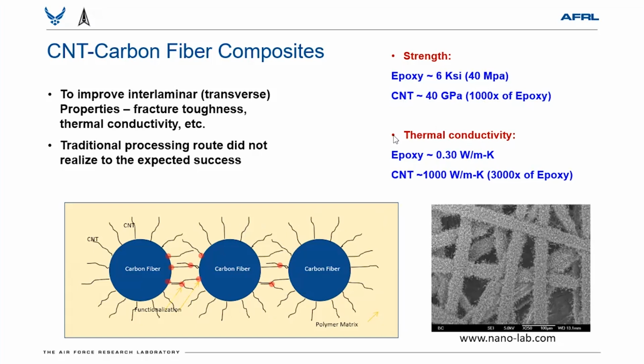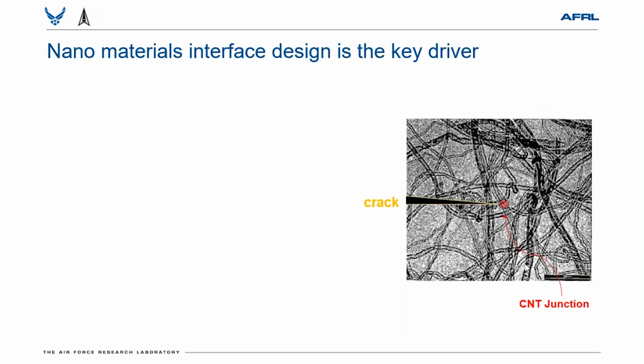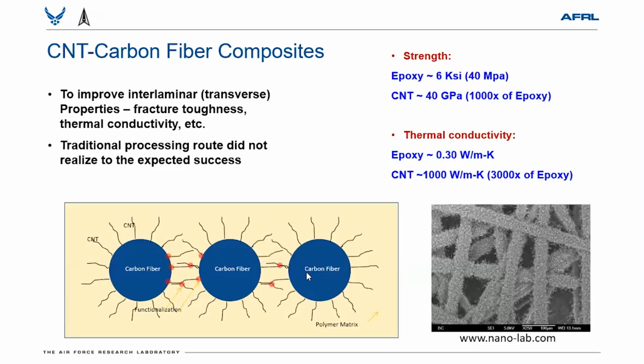Same is the story for thermal conductivity. Thermal conductivity for epoxy is 0.3 watts per meter Kelvin, whereas the CNT conservative estimate is 1,000 watts per meter Kelvin. So even when 1% carbon nanotube is dispersed in polymer, you would expect a lot of improvement. But that has not been realized because of this interface issue that I'm going to discuss.